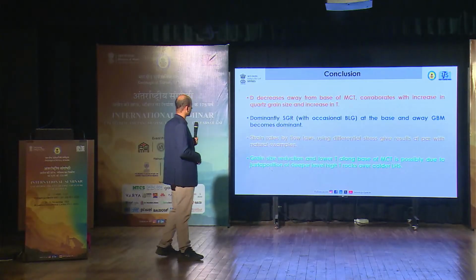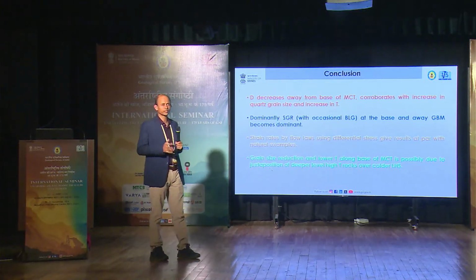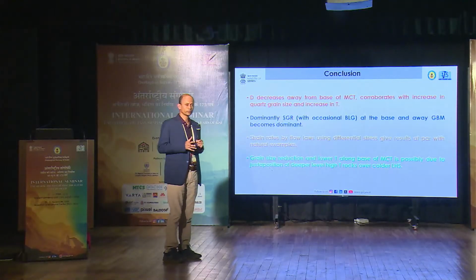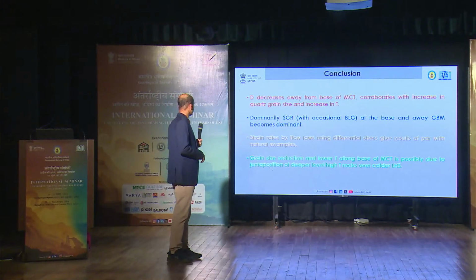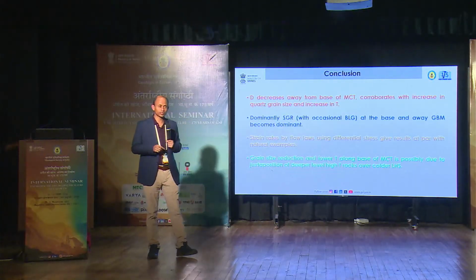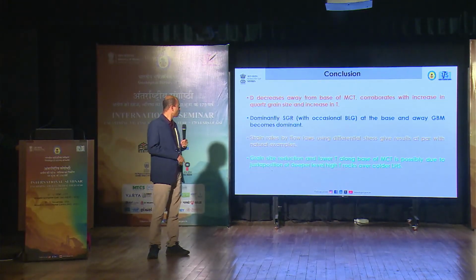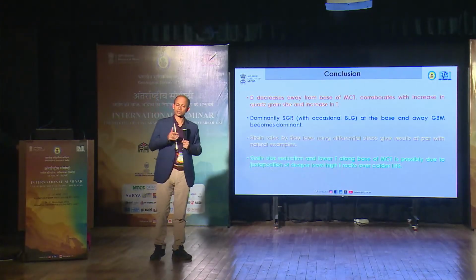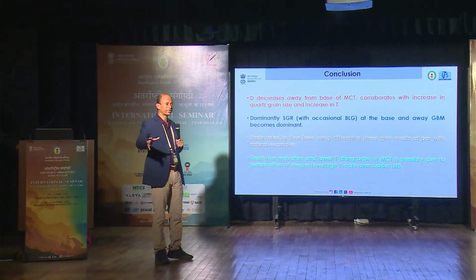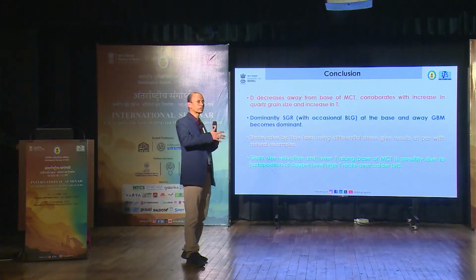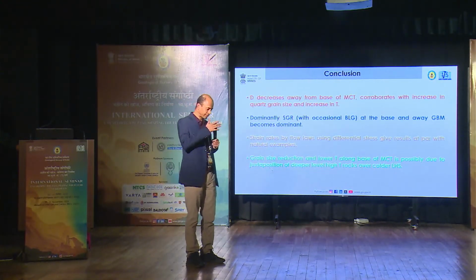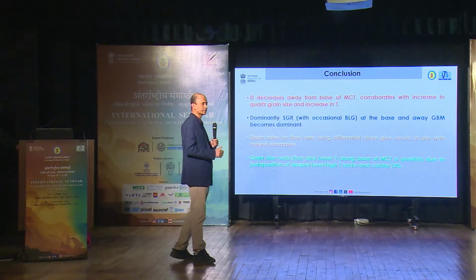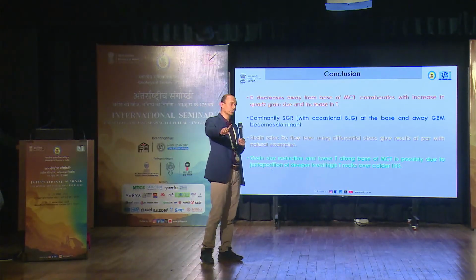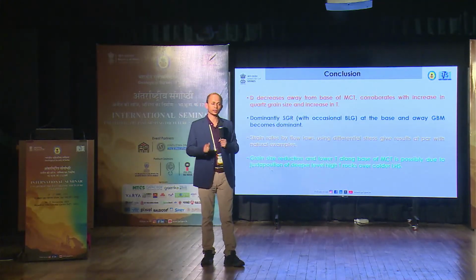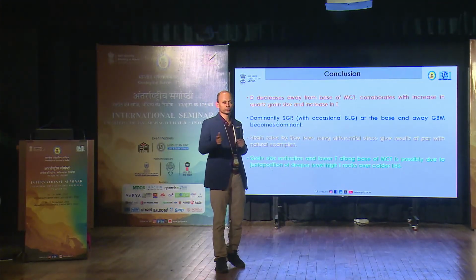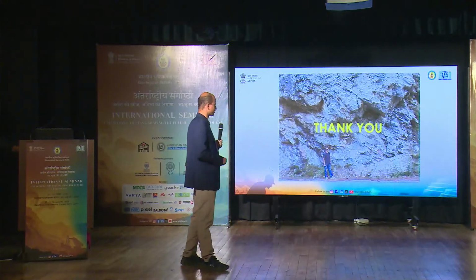Now the strain rates by flow laws using differential stress are giving us results which are at par with naturally occurring shear zones. And further, regarding the grain size reduction and the lower temperature at the base of the MCT, what we conclude is that this is because of the juxtaposition of the deeper level high temperature rocks which have come with the colder Lesser Himalayan sequence, and therefore at the base we get higher stresses and lower temperature, and as we progress away we see higher temperature and gradual coarsening in grain size. That's it. Thank you.